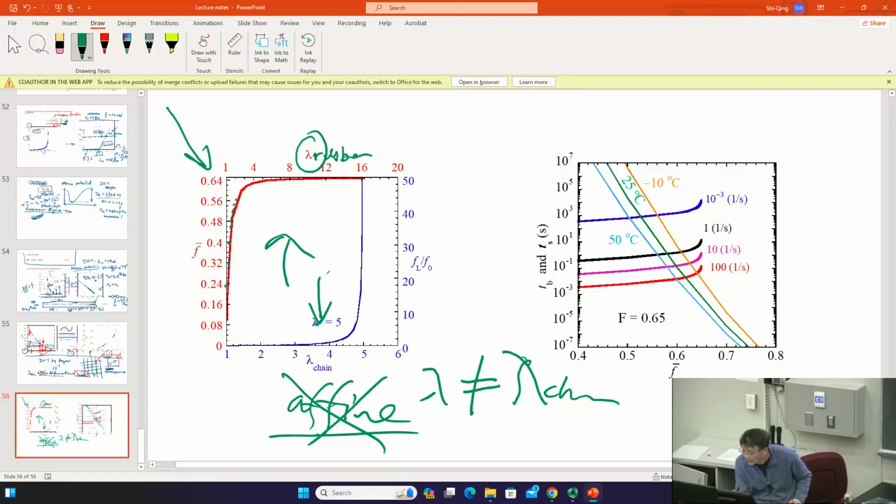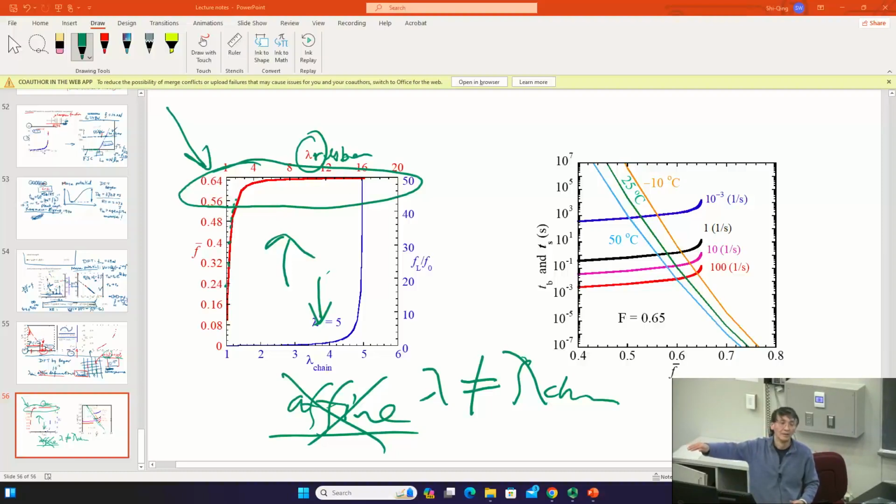I designed a curve so that it attains a reasonable number of between 0.4 to 0.7 instead of 1. So first time I tried it all the way to 1. Remember, 1 occurs instantly, if force is 1, and it gives you a very weak capturing of this feature, so it doesn't work.